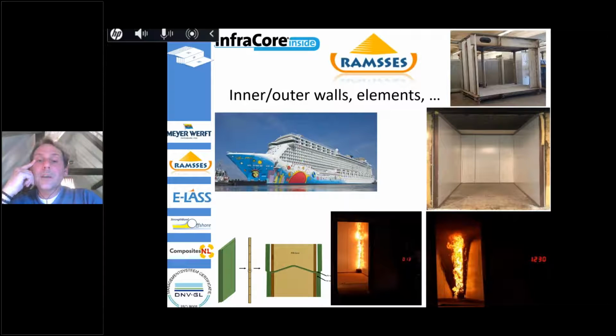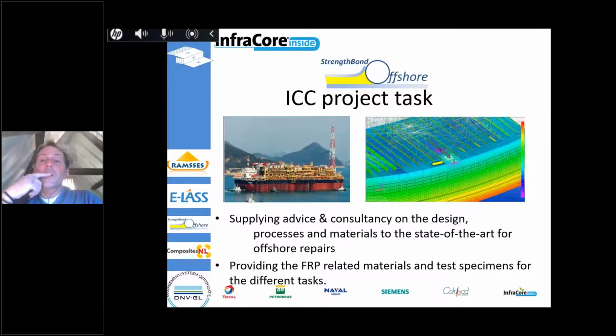So it's a structurally loaded structure which can withstand 60 minutes of fire under loading, without a temperature rise which exceeds a certain threshold on the backside, and with a maximum allowable deflection. So again, without added passive fire insulation, it's just the bare composite structure which has reached this FRD 60 certificate.